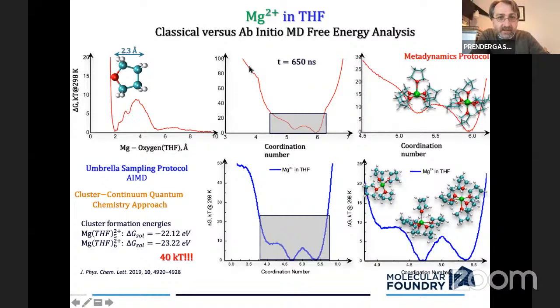Okay, then if we do a similar free energy analysis, but this time the coordinate that we're exploring is the coordination number, so the number of molecules bound to the magnesium, you can define that as a continuous variable and then scan it in the free energy. And what you find here is that there are multiple minima for the free energy difference with respect to coordination number. So that's interesting. That says that in the simulation, you might expect to see a mixed population of both species. Before, we had said that if you began with 6-fold, you stayed in 6-fold. If you began with 5-fold, you stayed in 5-fold coordination.